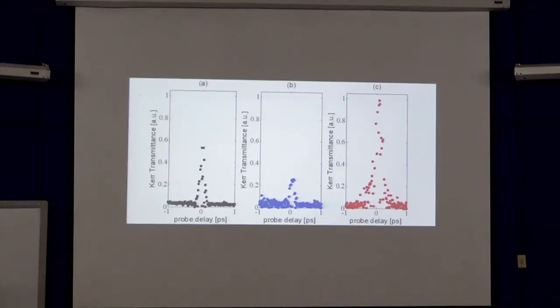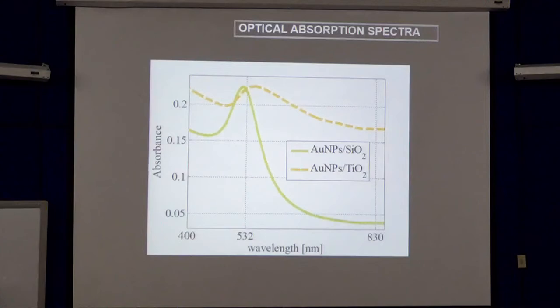In this case, this is a femtosecond pulse, not picosecond pulses. So the sample must have a faster temporal response. And something that also happens with these samples is that when you use, for instance, the green wavelength for testing the sample,